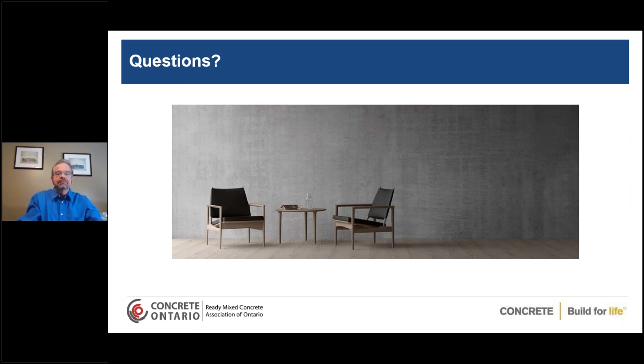So I have one quite specific question here. For the VMAR3 to be used as a pump aid for poor quality aggregate, what dosage would you recommend? Well, that would depend on the mix. You'd have to see how harsh the aggregates are, but typically you're probably in the 200 maybe to 400 milliliters per 100 kgs, something like that, maybe less. It depends on how bad the aggregates are. Great. You have to test and see.